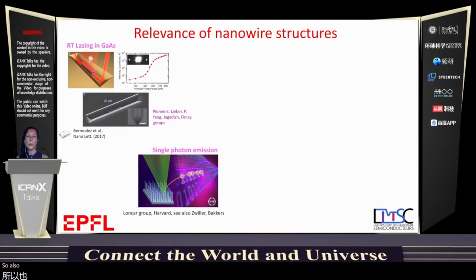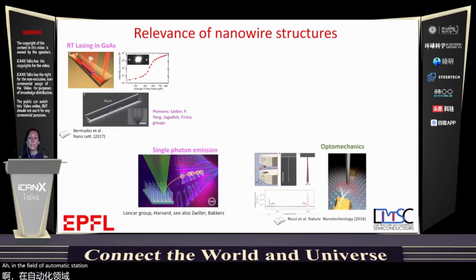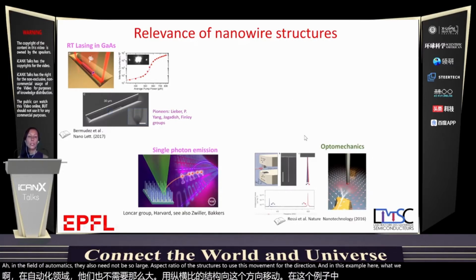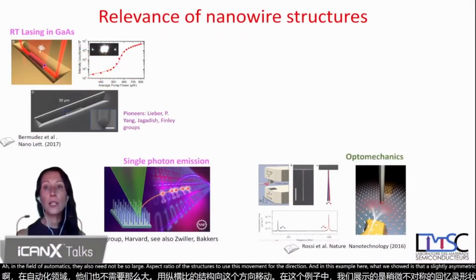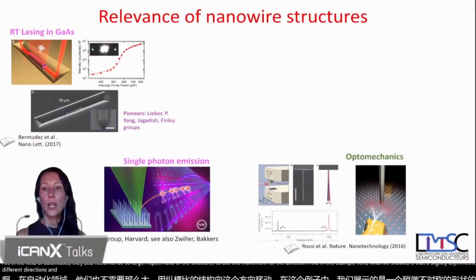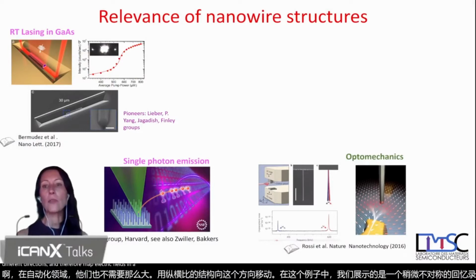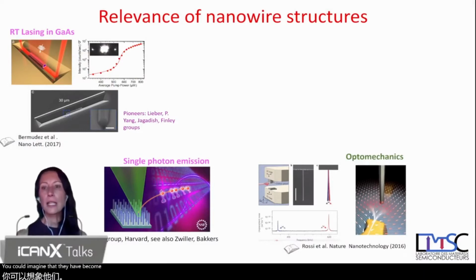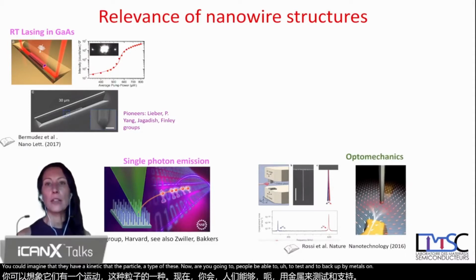In the field of optomechanics, they also use the large aspect ratio of the structures to use this movement for detection. In this example, what we showed is that a slightly asymmetric shape of the nanowires allows one to sense electric fields in different directions and therefore map electric fields in a planar way. You could imagine that by having a magnetic nanoparticle at the tip of these nanowires, one would even be able to test and map magnetic fields on a planar surface.